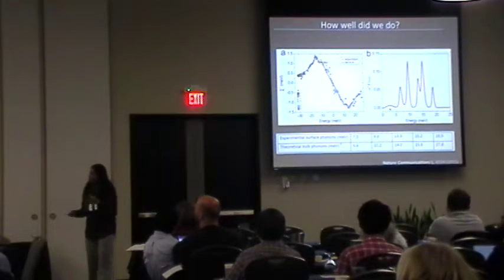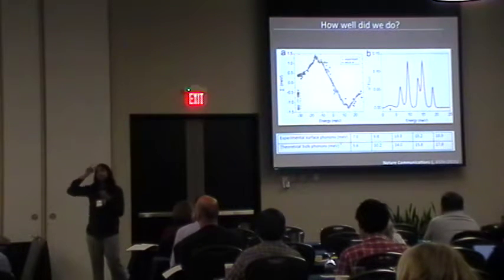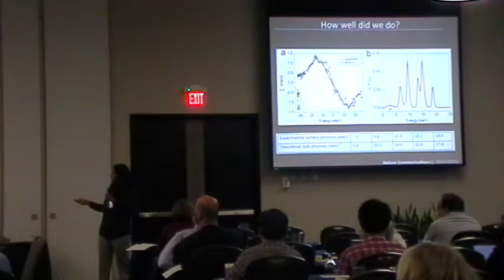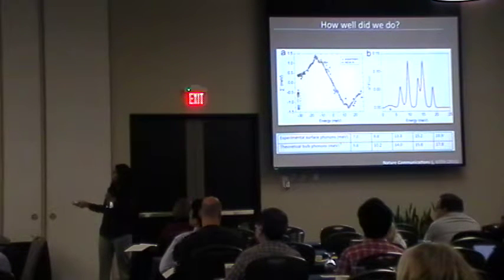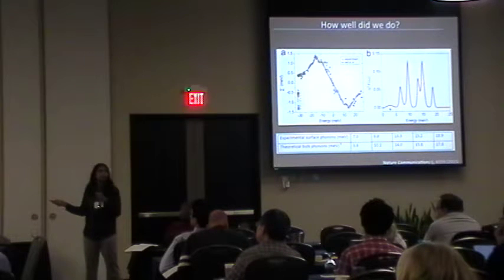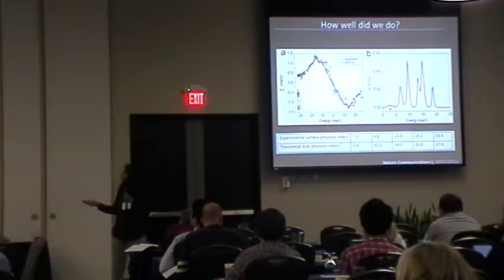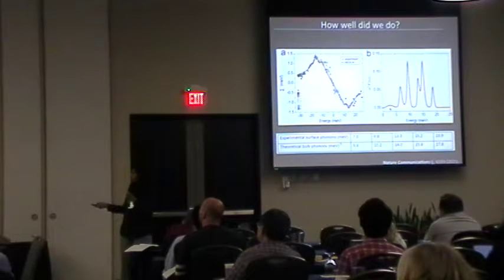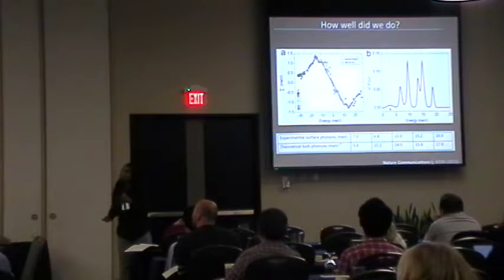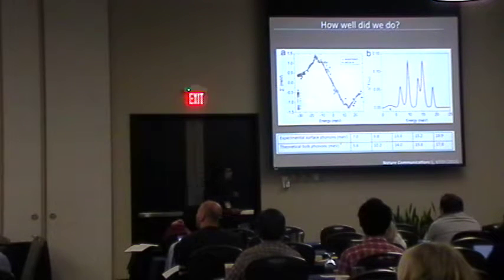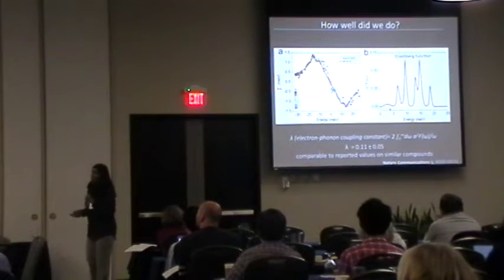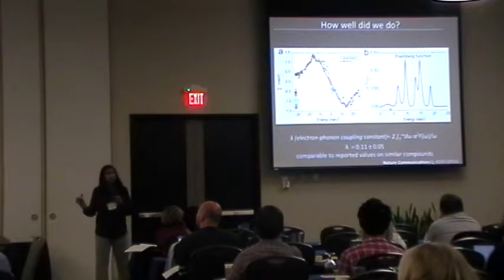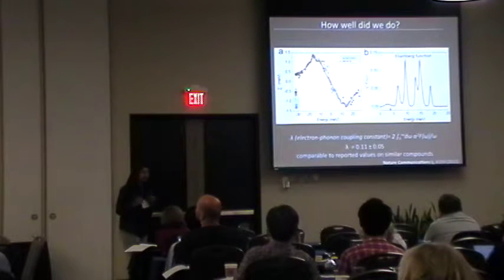Okay, and then the question is, how well did we do? Well, actually, here each peak is a phonon peak. There are no actual measurements of this in this material, but you can compare the phonon energies with theoretically predicted bulk phonons, not surface phonons, and you can see that we're within a milli-electron-volt for most of the phonons in this system, okay? So in that sense, we've done pretty well. Okay, and we can get lambda, and this is very small. So this is all I have to say about electron-phonon coupling.